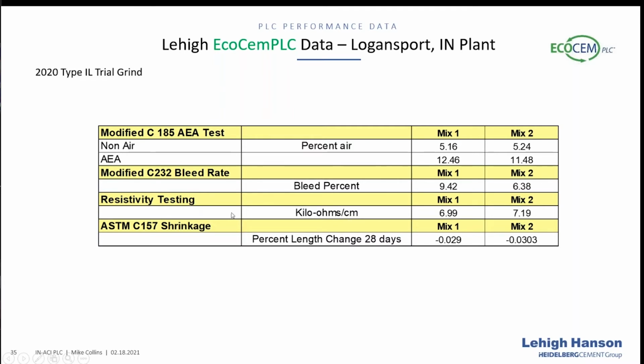Resistivity testing, we have a ResiPod unit at our lab, fairly close, a little more dense in the PLC mix as we would expect, again, with that increase in fines content. Something that is one of the biggest tests that we run in our lab is a C157 shrinkage test. Almost identical, 0.029, 0.030. So again, the shrinkage is a non-issue and very equivalent from mix to mix, regardless of powder in that situation.